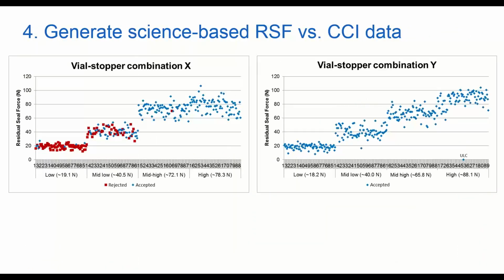Here is another set of RSF CCI correlation data, but plotted differently. And this also shows a few things. Here we're looking at two different vial stopper combinations. Again, looking at the residual seal force, different sample sets. So actually what we're plotting here are residual seal force sample sets. So starting from low residual seal force, these are loosely capped and crimped vials, up to the high capped and crimped vials. So you can see 4 different capping settings were used here to produce 4 different RSF groups, going from low capped or loosely capped to tightly capped.